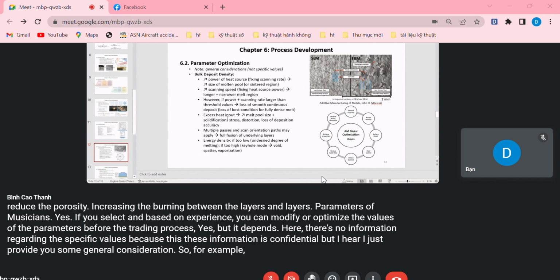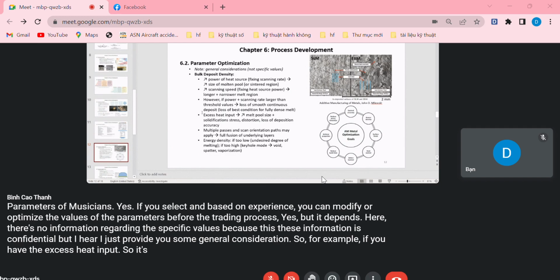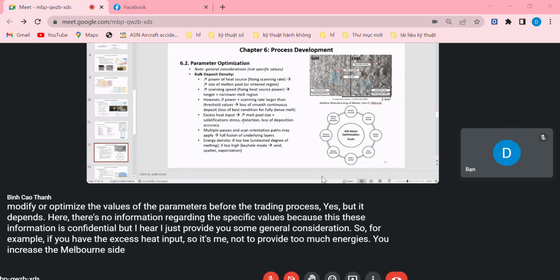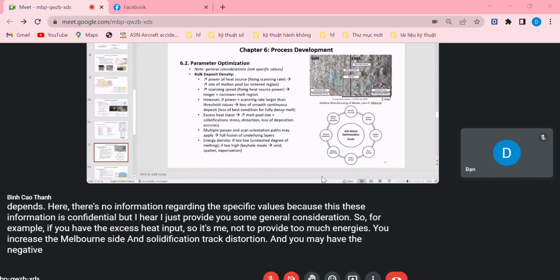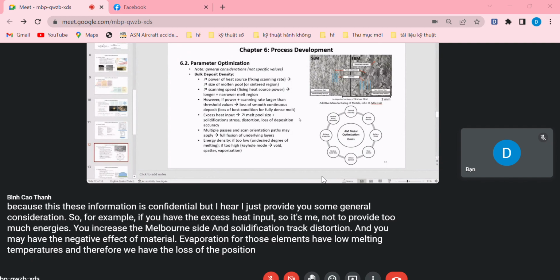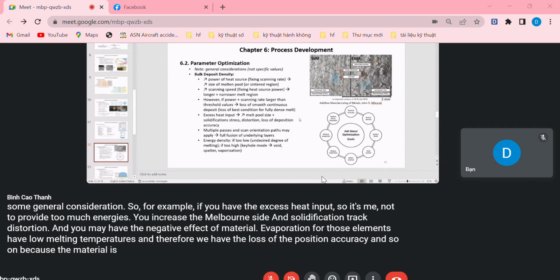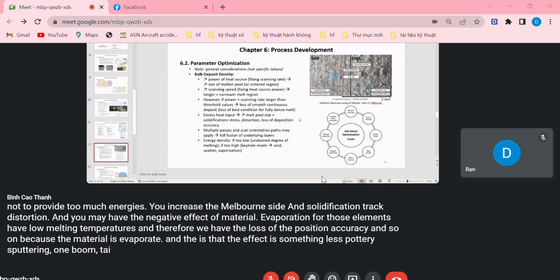For example, if you have excess heat input, meaning you provide too much energy, you increase the melt pool size and solidification stress distortion, and you may have the negative effect of material evaporation for elements with low melting temperatures. Therefore you may have loss of deposition accuracy because the material evaporates, and the effect is something like sputtering, which negatively affects the accuracy of the part for sure.